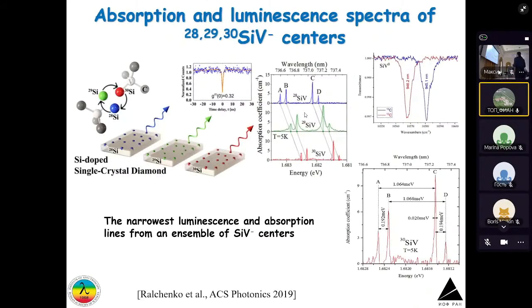There is another example of using our setup. We investigate the silicon vacancy centers in CVD diamonds with different silicon isotopes. And here we observe the narrowest luminescence lines from an ensemble of silicon vacancy centers. So you see there are different isotopes. It's an isotope shift with different silicon 28, 29, and 30.